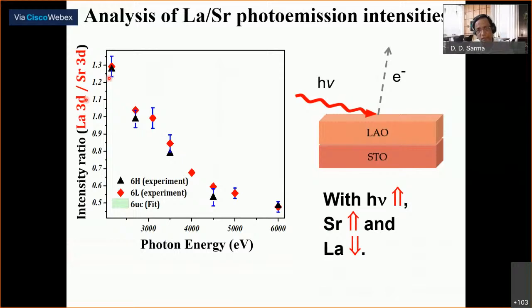I've plotted the data of lanthanum 3d core level intensity normalized by the strontium 3d core level intensity as a function of the photon energy. And you can see indeed this ratio of intensity is going down, telling me that lanthanum aluminate is on top, strontium titanate below. But I didn't have to do this complicated experiment going to a synchrotron radiation to tell me that lanthanum is on top, strontium below, because that's how I've made the sample. And also my cross-sectional TEM did show me that lanthanum aluminate is on top and strontium titanate below. My interest is to know, at this interface, do I have intermixing across lanthanum and strontium? Can I extract that from this information?